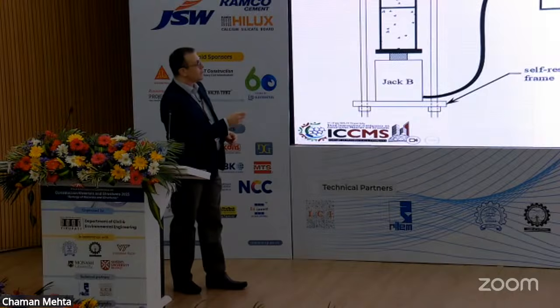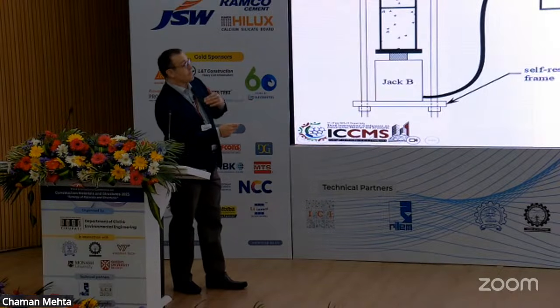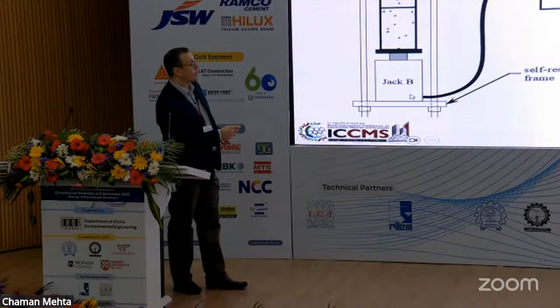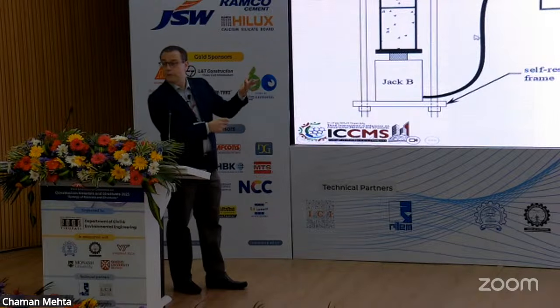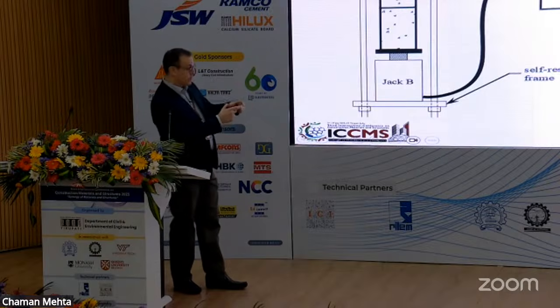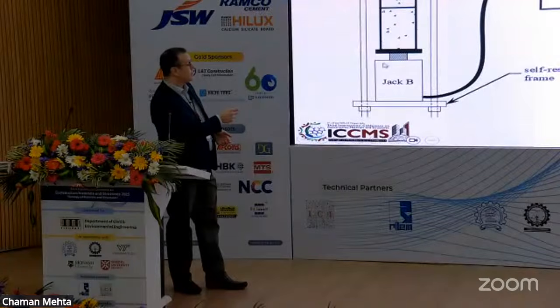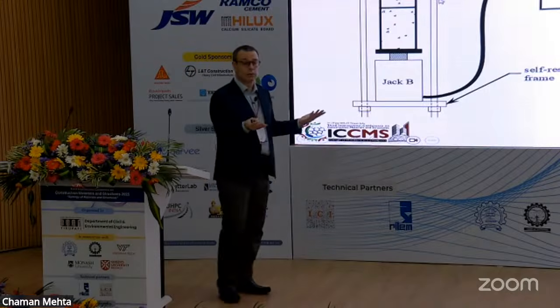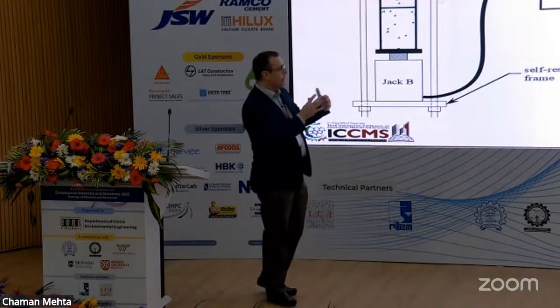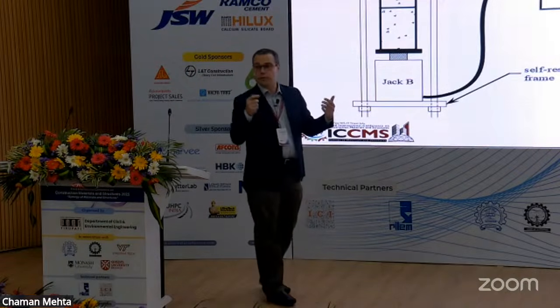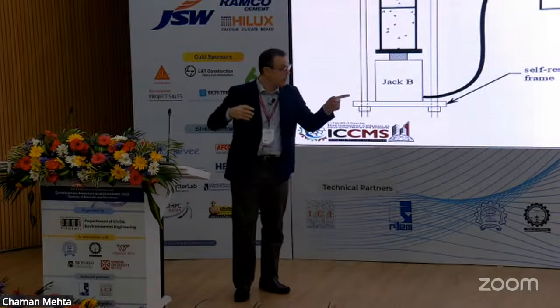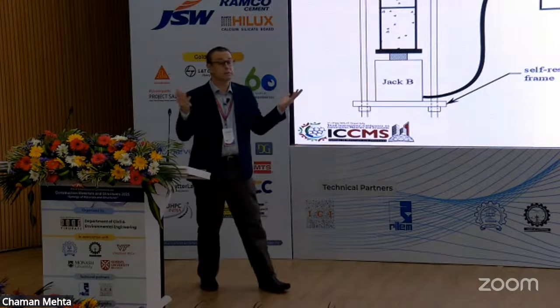And so basically, we spent some time. This, I would say, was one of the hardest test rigs I've done, because we spent a lot of time changing the jacks. Basically, we put a sustained load, like a self-weight, a piece of steel or concrete, against a smaller jack, a small ram, which builds up a pressure, and then applies the pressure through a larger jack, and they can keep it loaded. We tried different sleeves, and then we got a system where once you push up the weight, it stays on for 3-4 months. So it's brilliant, it's very comfortable. And we applied that to different scenarios.